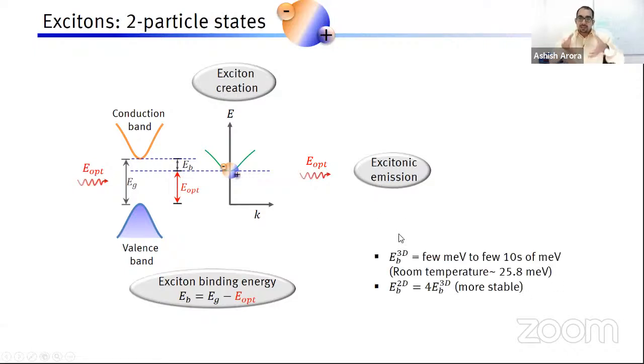In three-dimensional semiconductors, such as three-dimensional gallium arsenide or silicon, the binding energies of these excitons can vary from a few milli-electron volt to a few tens of milli-electron volt. Now, when we compare it with room temperature, which is of the order of 26 milli-electron volt, this is small. So therefore, three-dimensional excitons are not very stable at elevated temperatures or room temperature. However, theoretically, if we create a two-dimensional semiconductor, then the binding energy of this exciton can be 4 times that of the 3D exciton. So therefore, it is more stable. So this is one of the reasons why two-dimensional excitons are promising platforms for studying semiconductor physics at elevated temperatures.